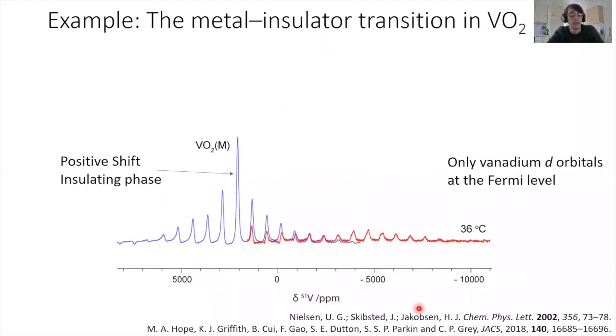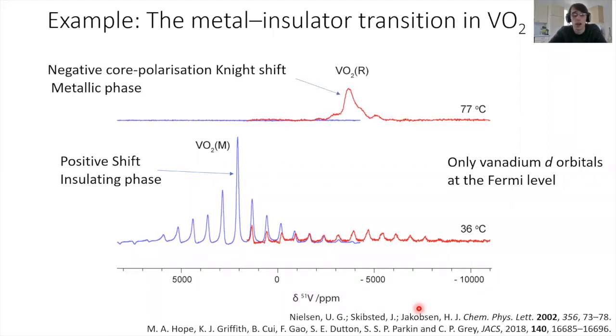So one example of this is in VO2. This is something I looked at during my PhD. And so VO2, vanadium dioxide, is interesting because at room temperature, it's an insulator. And so in the 51V spectrum, you end up with a shift of 2000 ppm. But then if you heat it above 67 degrees centigrade, it transitions into a metal. And this results in a 7,000 ppm shift in the 51V spectrum.